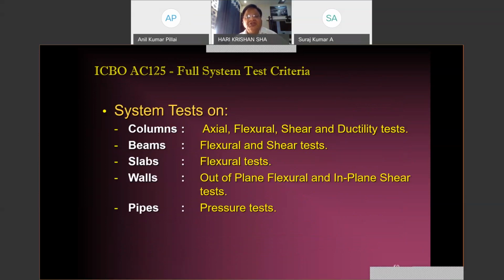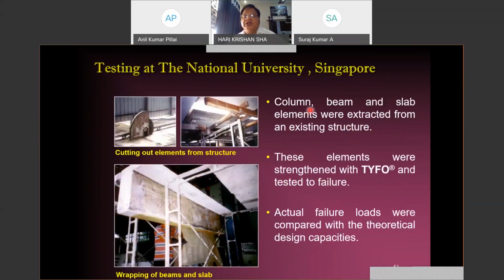As far as this material is concerned, the material was widely tested at the National University of Singapore. And you can see that the column, beam, and slab elements were extracted from an existing structure. And these elements were strengthened with TYFO and tested to failure.